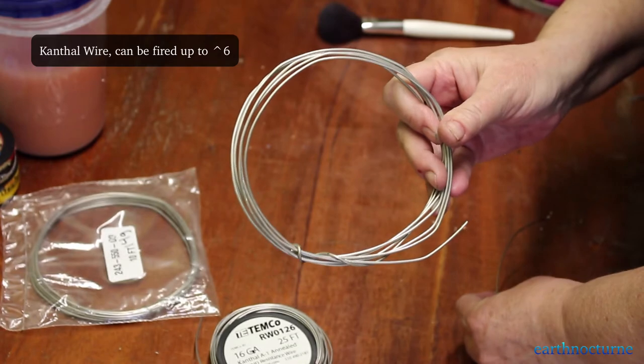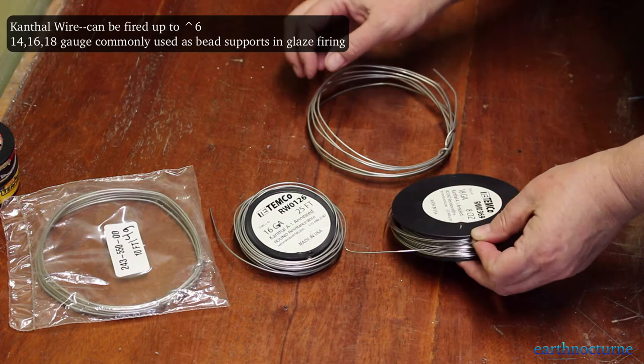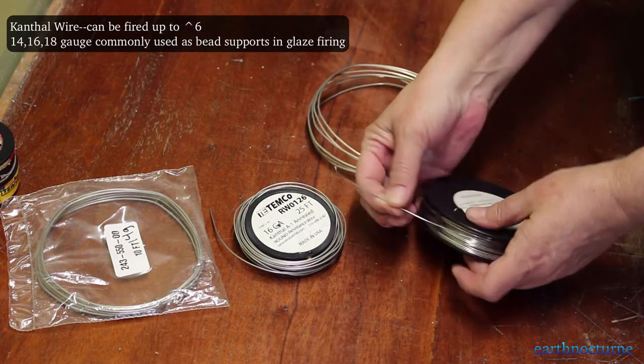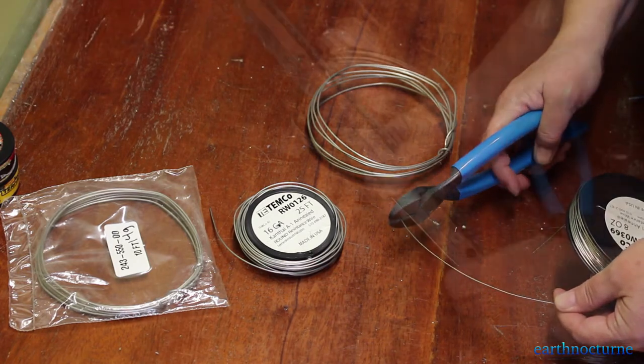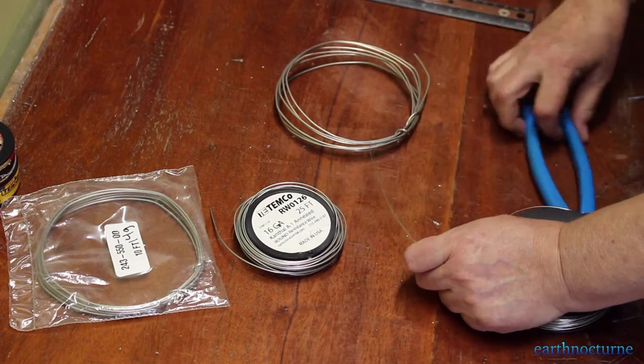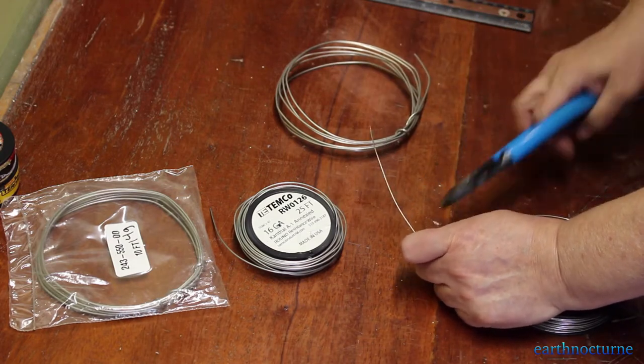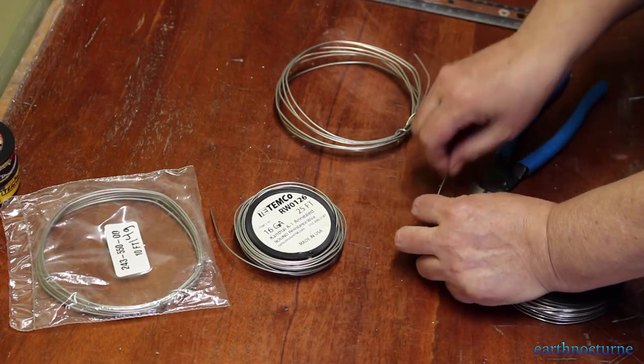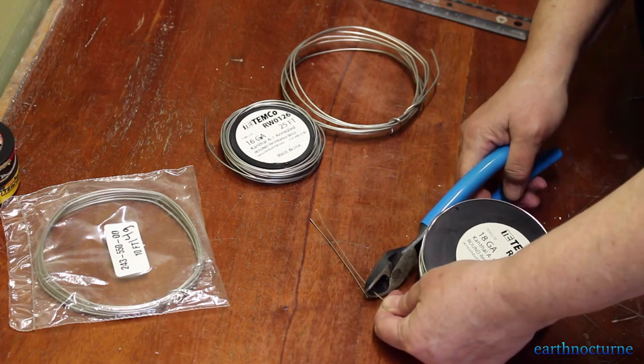This is Kanthal wire in 14 gauge. This is what I will be using to hang the beads in the kiln during the firing. I also have 16 and 18 gauge wire which I use for very light beads, as it tends to bend if it has a heavier bead on it. Now I'm cutting these to about three inches for my needs. You may need them longer or shorter depending on the space between posts you'll be using.